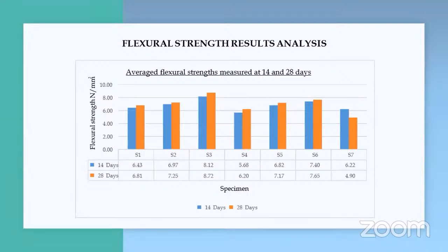This figure shows the flexural strength test results. Specimen S3 indicates significantly higher flexural strength compared to the control specimen. Furthermore, when the PVA content was increased up to 3% in specimens S4 and S7, the flexural strength at both 14 and 28 days had noticeably reduced compared to specimens S3 and S6 respectively. This could be due to the covering of the cement and RHA particles by the high PVA polymer content in specimens S4 and S7.